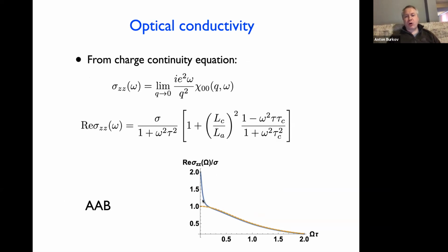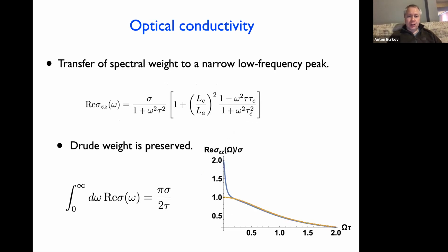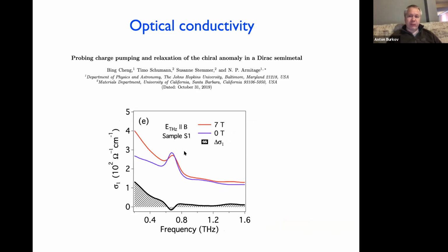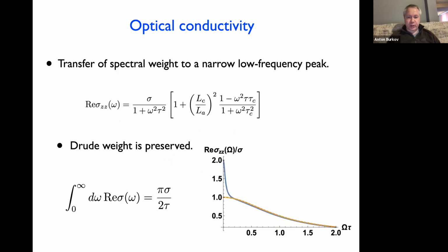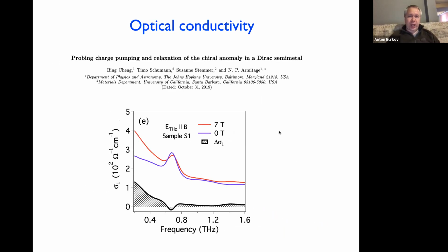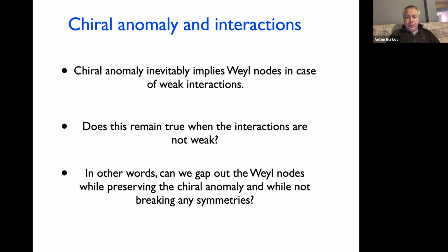Its width is proportional to the chirality relaxation rate, 1 over tau c, instead of the momentum relaxation rate 1 over tau. And since tau c is typically very large, much larger than the momentum relaxation time, there's going to be a narrow peak in the optical conductivity whose width is proportional to 1 over tau c, and the height is proportional to the square of the magnetic field. This effect may have been seen already, although it doesn't look quite as spectacular as my picture here, but it may have been seen in cadmium arsenide. That's another topological semimetal material.